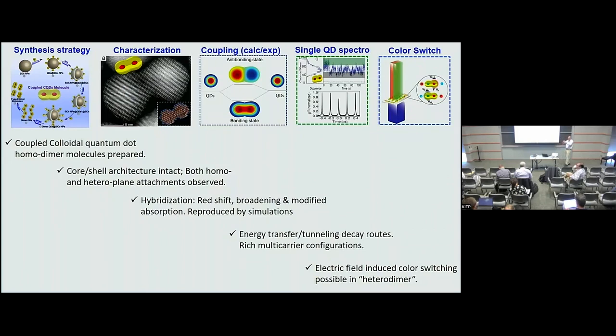Actually, it linked tip to tip because of the high reactivity of that tip region. In this bow tie, we did see enhanced polarization for the dimer emission. The monomer in that case is not polarized, there is no preferred axis, but the dimer did show preferred polarization along the bow tie axis, in line with what you were asking about, if I understood correctly. Yeah.